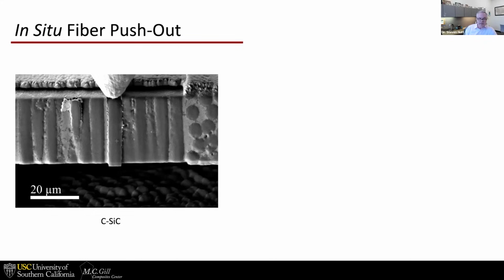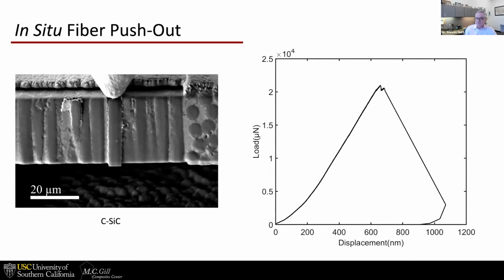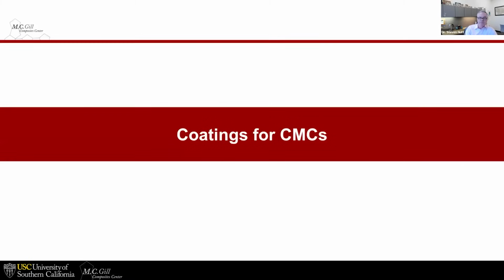basically fiber push out. We used a focused ion beam to machine trenches underneath these little ledges here and machine a very smooth flat surface that we can use a flat bottomed indenter to push out individual fibers. We use the SEM imaging capabilities to position fibers directly under the indenter. When we measure load versus displacement, we can then use that as a tool to discriminate the effects of different fiber coatings, different process histories.